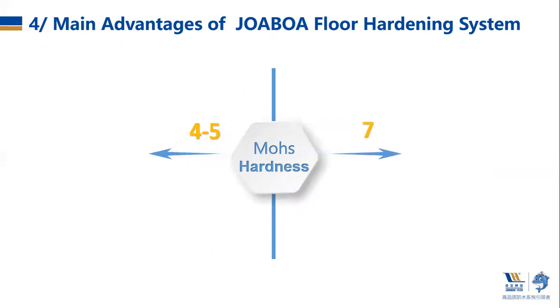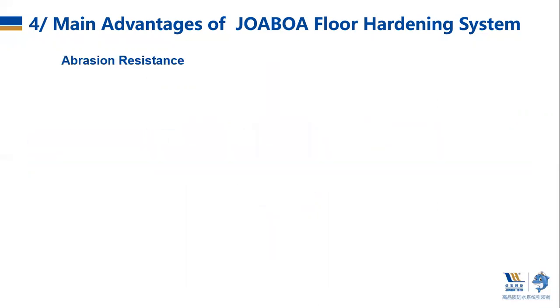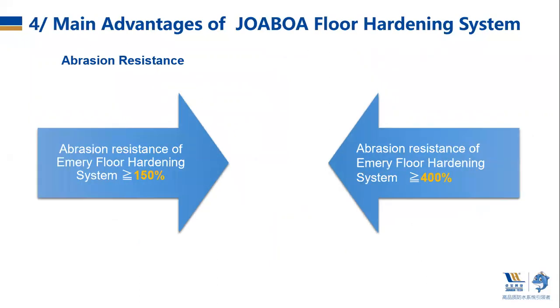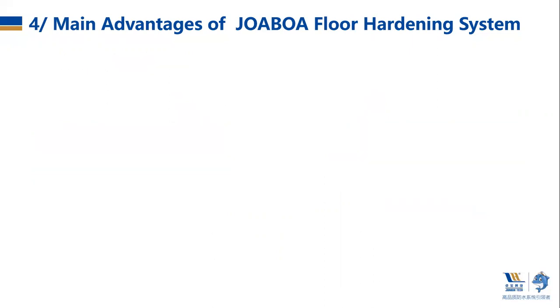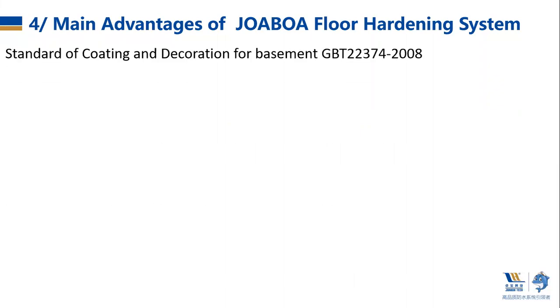For hardness, emery floor achieves level 4 to 5, while Joaboa system reaches level 7 to 8, with 3 to 4 levels increased of fresh concrete. For abrasion resistance, emery's floor is over 150% and our system is 2 times more, over 400%. For slip resistance, the coefficient of friction is over 0.56.